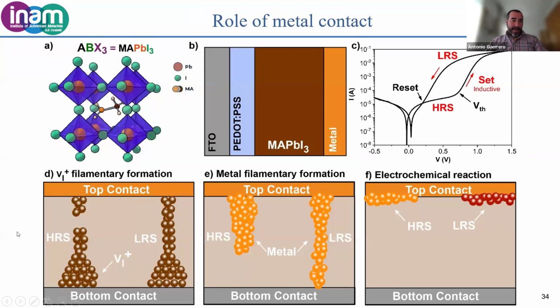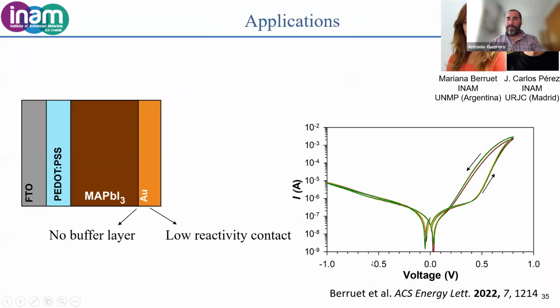This is like an overall picture of the two different situations we can have. So we could have the halide vacancies forming filaments of conductive halide vacancies, or we could have the contact forming filaments of metal. But also we know that there can be electrochemical reactions, and these electrochemical reactions between the perovskite and the contacts can play also a significant role.